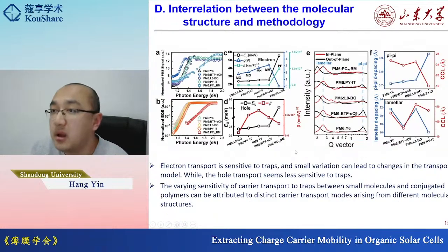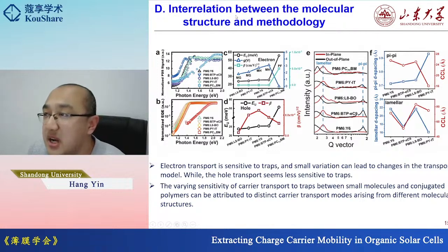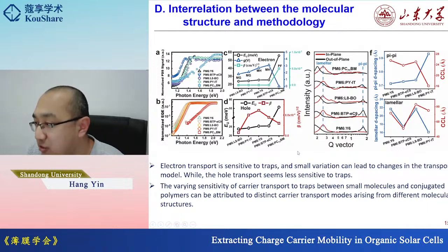And then we just study the interrelation between the molecular structure and the methodology. We can observe the electron transport is sensitive to traps, and a small variation can lead to changes in the transport model, while the hole transport seems less sensitive to traps, which is consistent with the published reports. And the varying sensitivity of the charge carrier transport to traps between small molecules and the conjugated polymers can be attributed to distinct charge carrier transport models arising from the molecular structures.